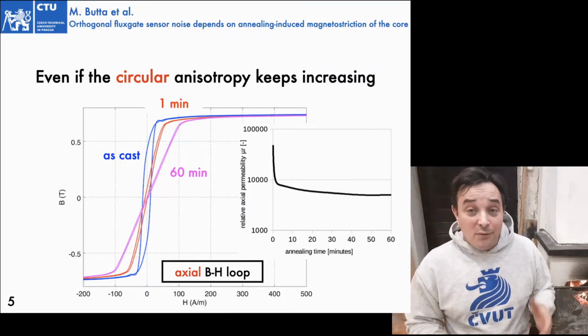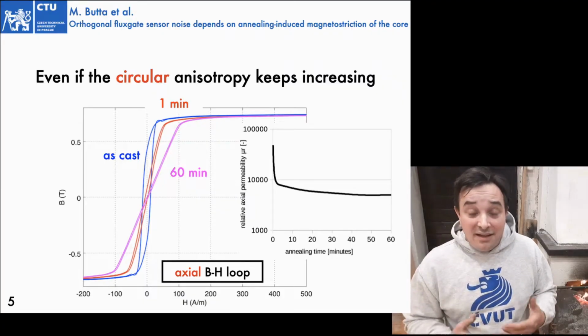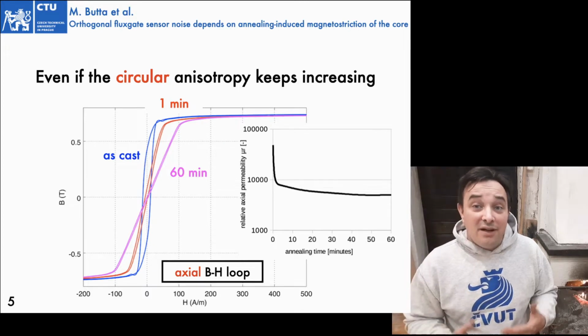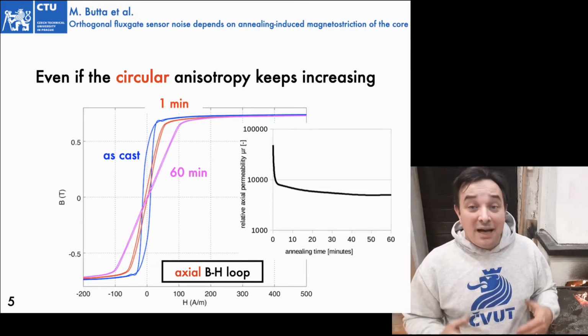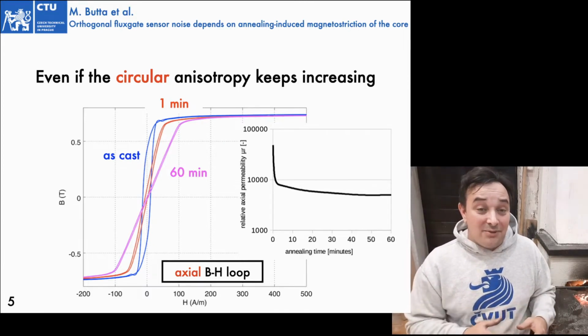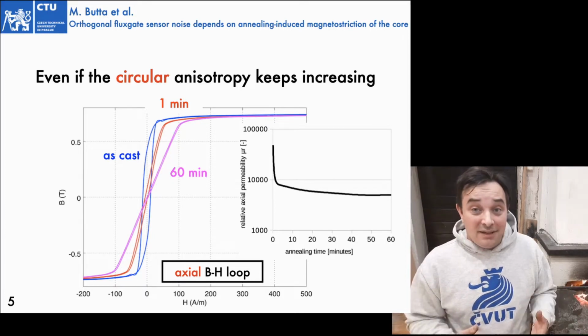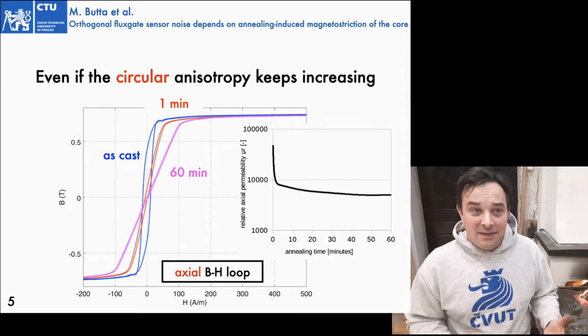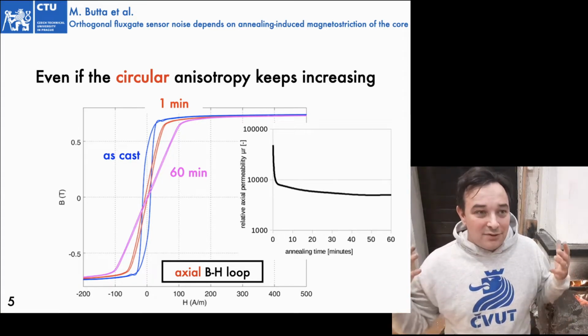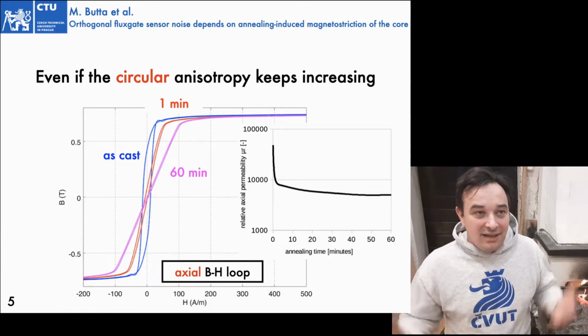In fact, if you watch this graph, you can see that even for 60 minutes annealing, you have a large circumferential anisotropy. Well, actually here you see it indirectly because you observe the axial BH loop. And you can see that in the axial direction, the wire just gets harder the longer is the annealing time. So yes, even for such a long time, you get large circumferential anisotropy. So what's the problem? Why do I get larger noise for long annealing time?